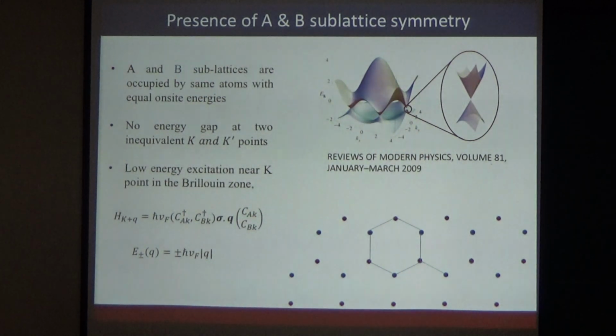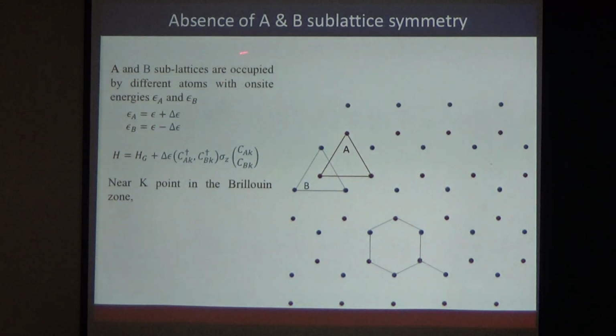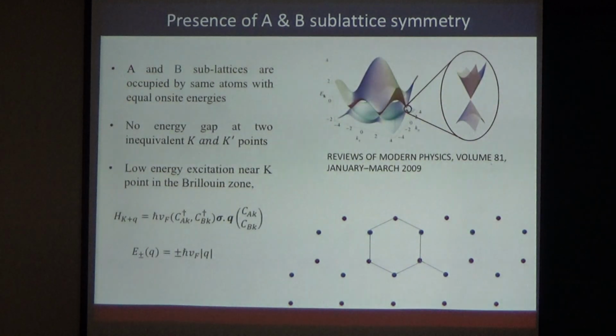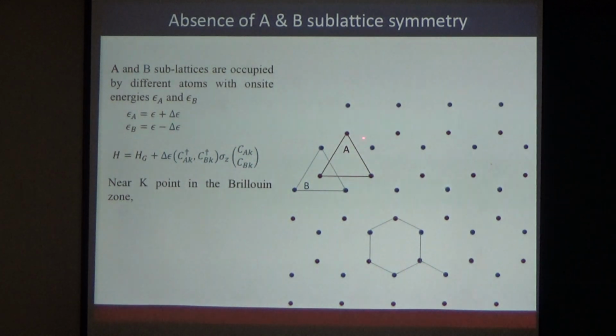It's linear, right? And now I have this sublattice symmetry, because here we had A and B sublattices occupied by the same kind of atoms, carbon atoms, so their on-site energies are equal. So the orbitals that were participating in the hopping, their energies are equal. Now if I change one of these sublattices to some different atoms, let's say A and B sublattices are occupied with different sets of atoms, so that the on-site energies are different, E plus delta E and E minus delta E, then the Hamiltonian will change by an additional term here, and that will give rise to the energy dispersion that looks like this.